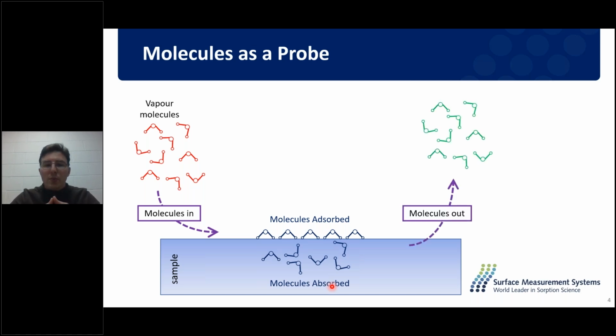So there are a few ways in which we can measure the influence of our probe molecules. We can see how the mass of this sample changes as we're introducing these molecules. We can also see how much we inject versus how much we detect. And that way you can get an idea of how much that material is retaining. In inverse gas chromatography, what we want to do is see how quickly or how slowly our probe molecules are going over our surface. So quite a different system to what you see with dynamic vapor absorption, but the way and the manner that we are introducing our probes over our sample reflects some similarities.